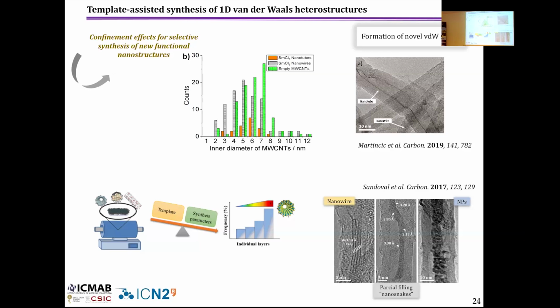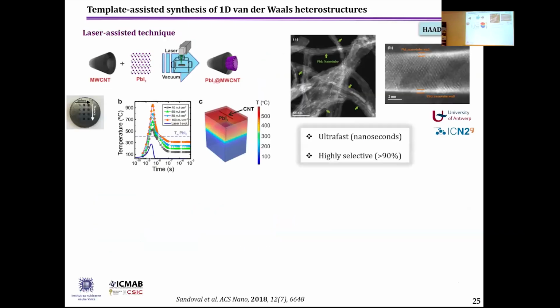Another advantage of this technique is that we were able to change the structure of the material by confining. This is an example of samarium chloride, which a structure in bulk is not layered, and when we confine this system inside the nanotubes, we were able to prepare a nanotube. So this is like a not very widely explored approach to change the crystallinity and the structure of the material by confinement.